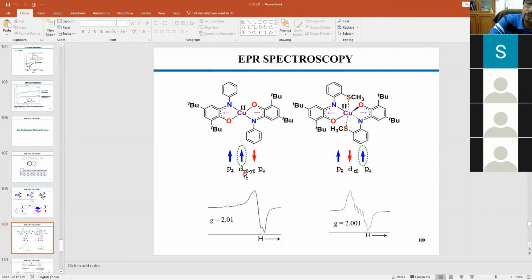So the unpaired spin of the copper is in x square minus y square. That's why it cannot couple with the pz orbital of the ligand bearing electrons. So it cannot couple, so it prefers to couple these two. On the other hand, this is the elongated setup, and this is your compressed setup. As a result, your dz square has the unpaired electron. So dz square and pz are symmetrically allowed to interact, and as a result, this set of electrons gets coupled,